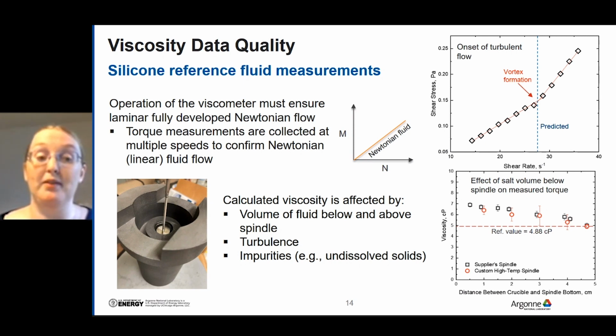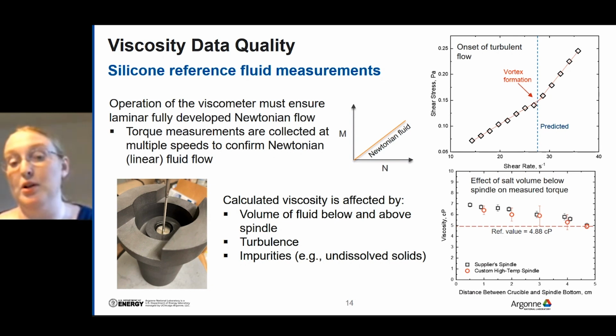We've also noted that the calculated viscosity can be affected by things like the volume of fluid below and above the spindle, which can cause vortices or non-fully developed flow to occur. So the figure on the bottom here shows with a couple of different types of spindles that the amount of fluid between the crucible bottom and the spindle bottom, the fluid below that spindle, needs to be maximized to a certain value before you can get very accurate data.